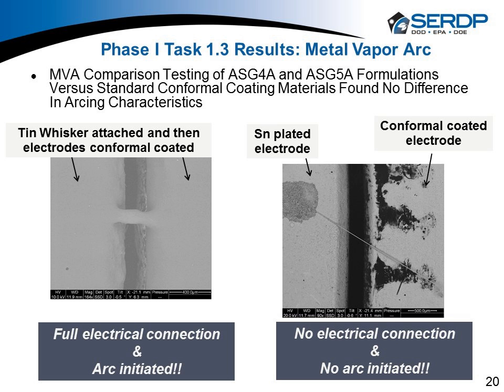And what we found was if the whisker is making connection underneath the coating, and of course we did this with acrylic, with parylene, and the liquid glass, you do make an electrical connection. You do get this to spark. It doesn't escape the coating, but you could actually see the whisker glow in here as it melted. So that had never been documented in the industry. We wanted to put that out there so that people could have that in their data sets.